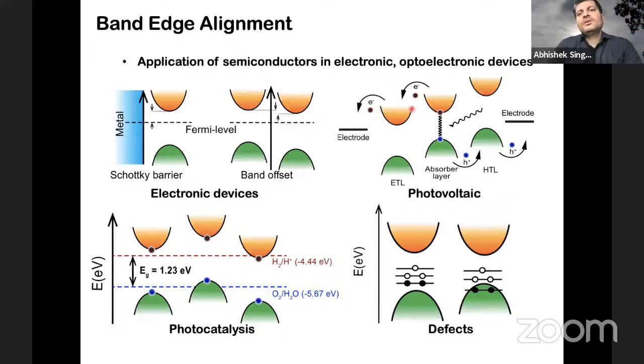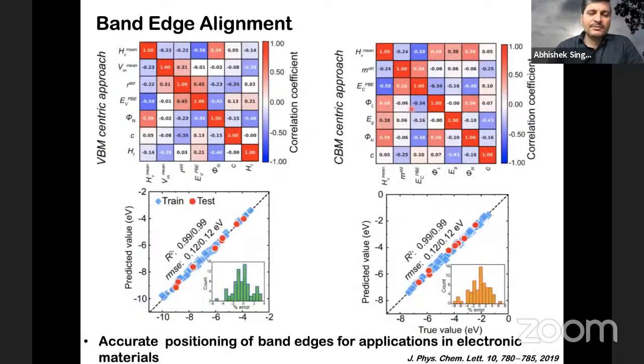What you get out of simple VASP calculations is not correct, because these numbers have no value actually, because there's no reference to it. So you have to refer it to the vacuum level and then get the accurate positions of these VBM and CBM. So we developed two models, one for VBM and one for CBM, and what we found is that the VBM model was good enough to predict both VBM and CBM. So one model was powerful enough, actually both of them do both. So you pick up any of these models, they would be able to give you both the position of VBM and CBM. And not only that, if you know accurately the VBM and CBM, then you get the band gap for free, because you just take a difference and you get the band gap.